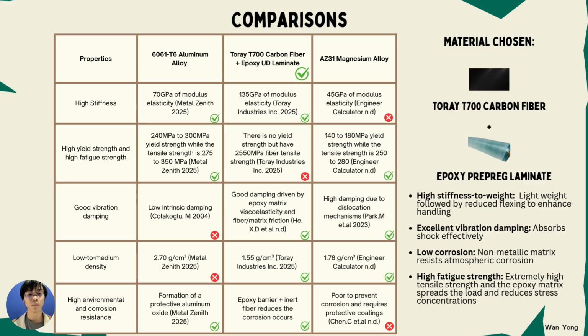When we look at the stiffness, which determines how much the material bends under load, the aluminum has a modulus of about 70 gigapascals, and magnesium is even lower at around 45 gigapascals, making both materials relatively flexible. In contrast, the carbon fiber composite reaches approximately 135 gigapascals, almost twice the stiffness of the aluminum, which allows it to resist bending more effectively and maintain better shot stability during use.